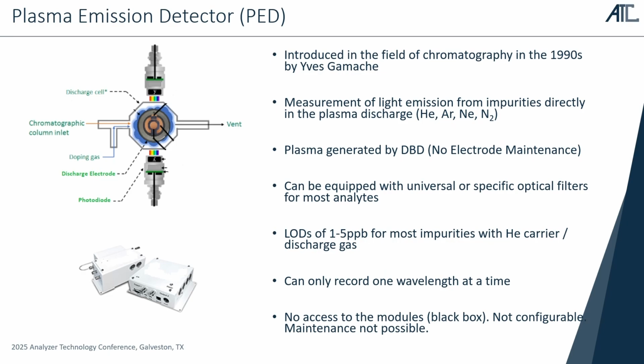So in the 1990s, Yves Gamache introduced the plasma emission detector, or PED, in the field of gas chromatography. And instead of using a photoionization mechanism from helium to ionize the impurities, it actually used the carrier gas, which goes inside the plasma chamber, and when the impurities reach the detector, they are ionized, and we measure light emission from the impurities that are ionized inside the plasma chamber. Then you can put some optical filters in front of the photodiode that measures light emission, and this optical filter can be universal or specific to the impurities that you're going to measure. It's a plasma that is generated by DBD, so there's no need for electrode maintenance. And this technology can reach a limit of detection of about 1 to 5 ppb for most impurities in helium discharge.